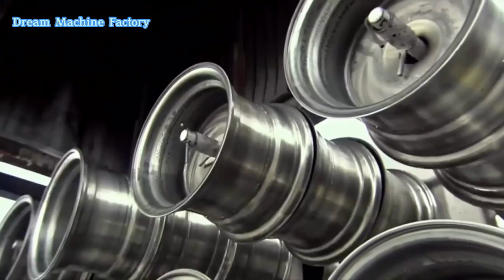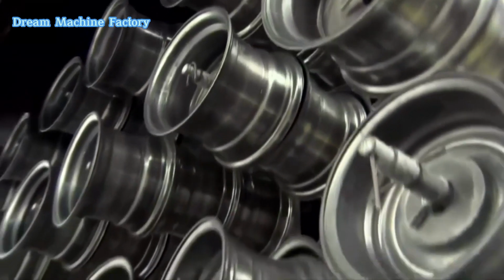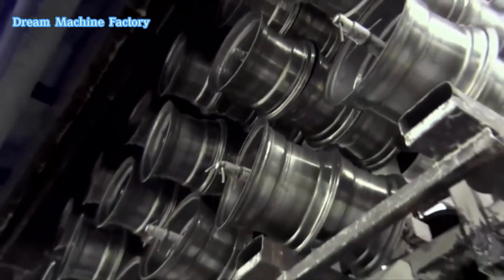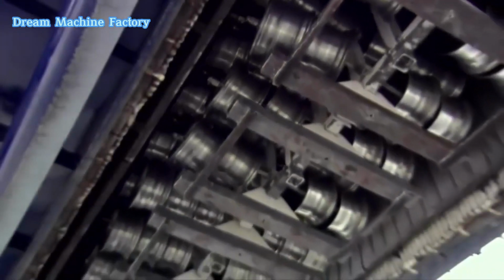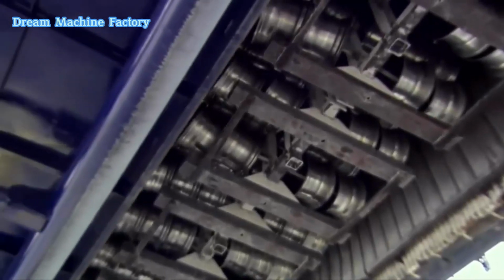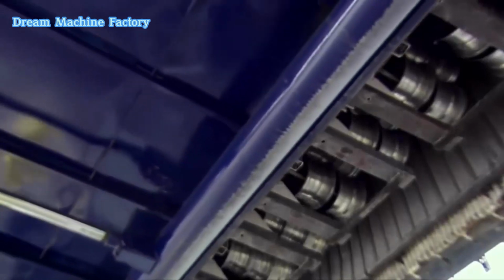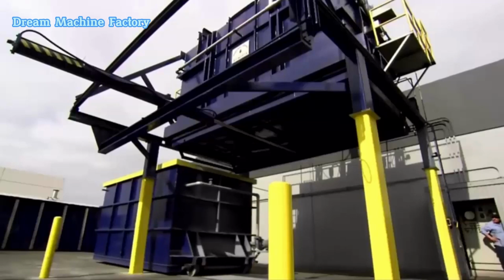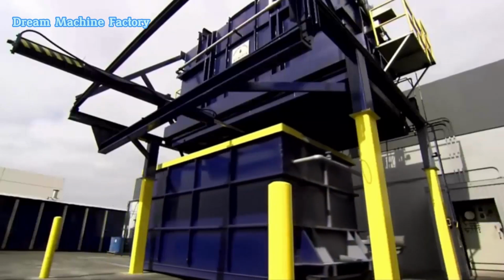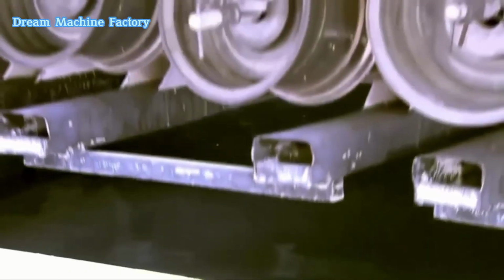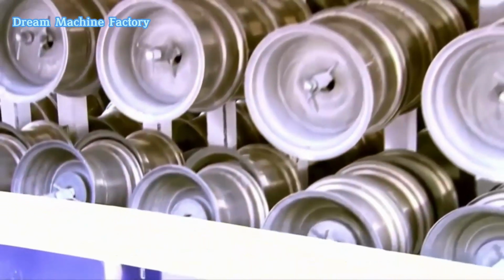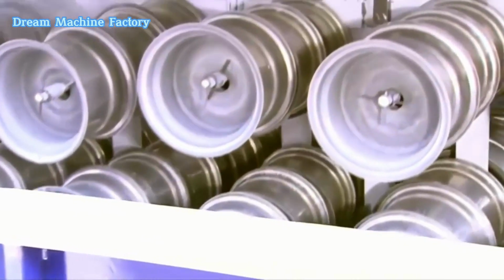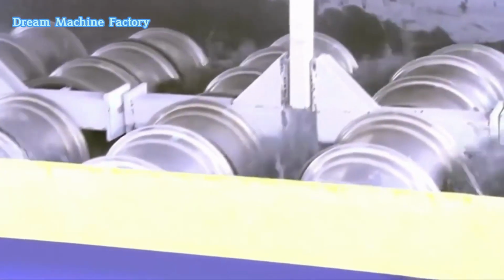To further enhance the wheel's strength and durability, it undergoes another round of heat treatment. The newly formed rims are placed inside a furnace, where they are reheated to around 530 degrees Celsius, 986 degrees Fahrenheit. This process is known as solution heat treatment and serves to refine the internal structure of the aluminum. Immediately after heating, the wheels are rapidly cooled in a quenching bath filled with cold water. This sudden cooling locks the refined molecular structure in place, increasing the wheel's toughness and resistance to fatigue.